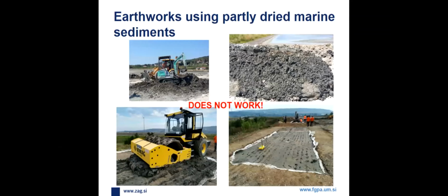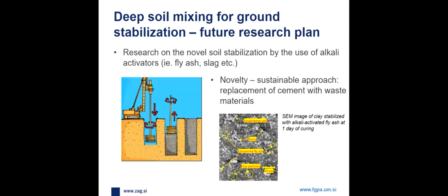So the next step was, can we use this material for simple earthworks? In the Port of Koper, they made several test fields, mixing this material also with lime, with cement, with different kinds of stabilizations. But in the end, we always found that if the material is far away from optimum moisture content, then you didn't do anything. So we have to dry the material first to a proper moisture, and then it can be used for earthworks. Actually, it's a material with quite good quality if it's dried enough. So this approach was not something that would satisfy the port administration. Now we are talking with them about two other possible solutions.